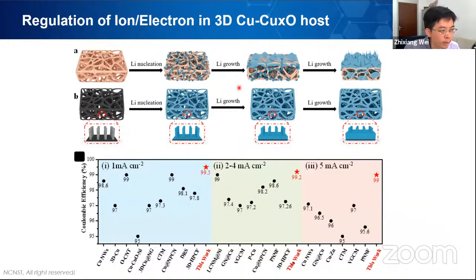Yeah, this is the performance. If you don't use the hierarchical structures and just use porous copper as the electrode material, because the lithium nucleation is non-uniform, you get lithium dendrites. Therefore, the performance is really poor. But if you use these hierarchical structures, the lithium nucleation and growth are quite smooth. Finally, you get a really good material with high Coulombic efficiency at different charge-discharge speeds. You can see this material is much better than reported materials using other strategies.